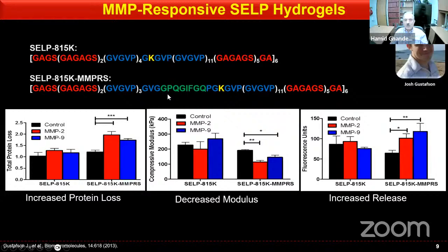And for doing so, we incorporated this green sequence, which is basically a sequence that's responsive to matrix metalloproteinases. Many tumors, as you're aware, they overexpress matrix metalloproteinases. That's in part the reason that basically tumor cells go elsewhere and metastasize. And so these enzymes are overexpressed in the tumor. In this case, we were interested to use this property of MMP responsive sequences to incorporate it into the polymer backbone in order to facilitate the degradation of these materials and hopefully enhance gene expression as well, due to the faster release of these viruses.